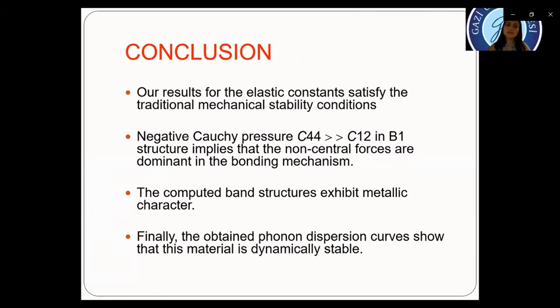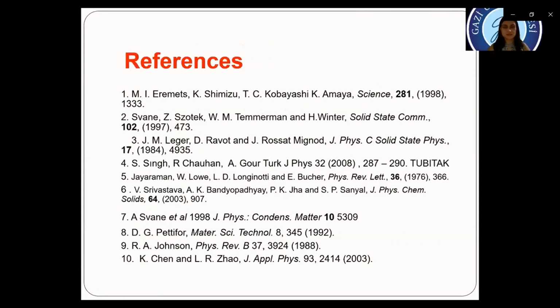The computed band structures exhibit metallic character. Finally, the obtained phonon dispersion curves show that this material is dynamically stable.